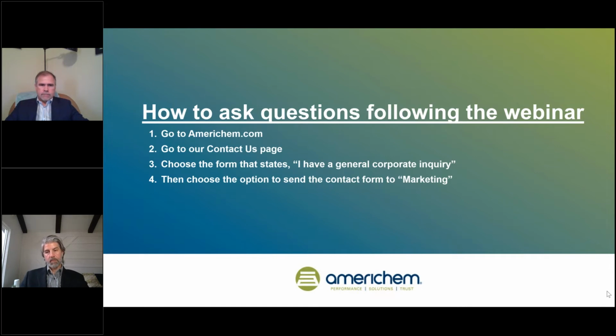Okay. Next one is, in which way are hydrophilic additives added in the extrusion process, spraying, etc.? Well, I think yes, to the question there, they are potentially added via in melt, as we've been talking about today. Also topically added, which I think Robert described to some degree in the discussion on another topic earlier. If you're going to do it topically, you're talking about addition, padding, and drying, versus the in melt, which probably becomes intrinsic to the fiber as produced, and it eliminates the need for those different secondary steps on the application.